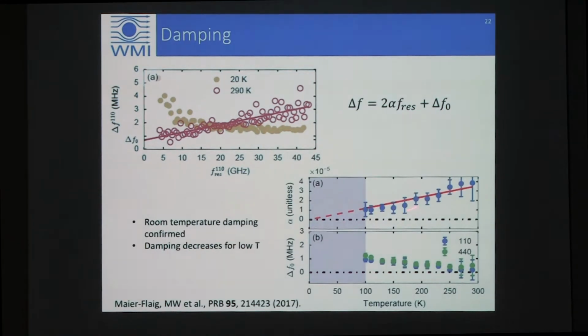But nevertheless, for the frequency range where we can get a solid linear fit, which is down to about 100 Kelvin, we do see that the damping really decreases. And it decreases, within errors, completely linearly, and that dashed line extrapolated down to the lowest temperatures suggests that the damping really goes away completely if you go to 0 Kelvin, whatever that means.